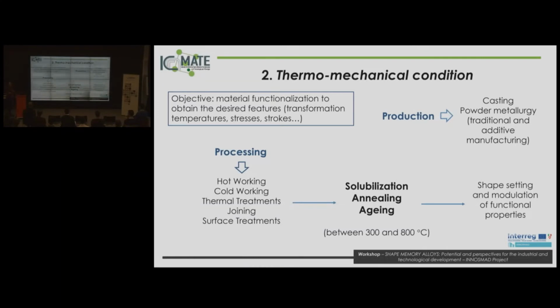Among thermal treatments, we can adopt some solutions such as solubilization, annealing, or aging, which are thermal treatments between 300 degrees and 800 degrees for different times, depending on the desired properties that we want to obtain. Indeed, the aim of this processing, and in particular of thermal treatments, is to have a shape setting of the component of the material, because if we heat up the shape memory alloy constrained in a mold, we can obtain the desired shape of this component. And the other important thing about the thermal treatments is that they allow us to obtain the desired functional properties.